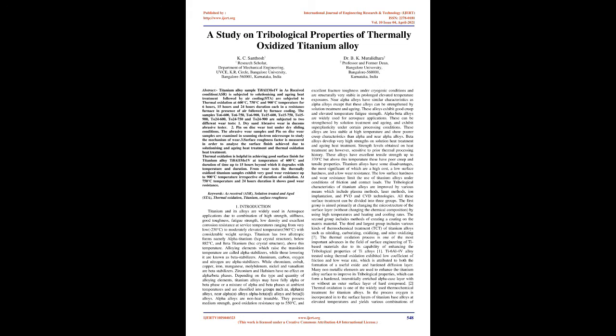From wear tests, the thermally oxidized titanium samples exhibit very good wear resistance up to 900 degrees Celsius temperature irrespective of duration of oxidation. At 750 degrees Celsius temperature and 24 hours duration it shows good wear resistance. Keywords: as received, ASR, solution treated and aged, STA, thermal oxidation, titanium, surface roughness.